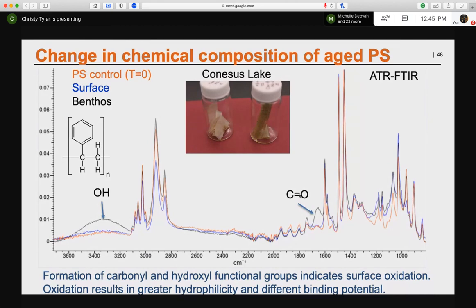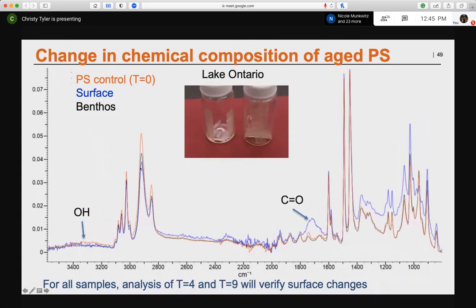If you look here, this is Conesus Lake. We can see that we're getting this oxidation species observed in the benthos species. But we can definitely see that there are some changes in the spectra of both the surface and the benthos. If we move on to the next one, Lake Ontario, we're really seeing no formation of hydroxyl groups, but we're definitely seeing formation of the carbonyl.